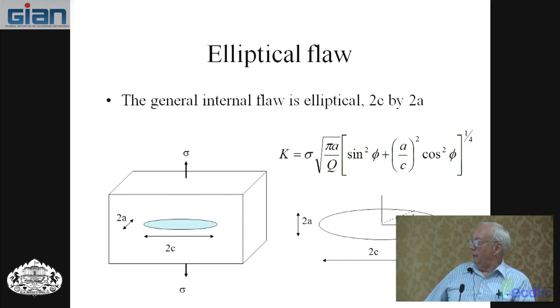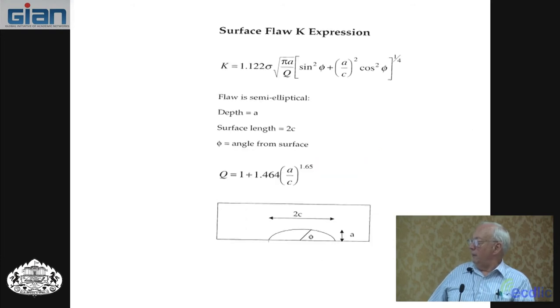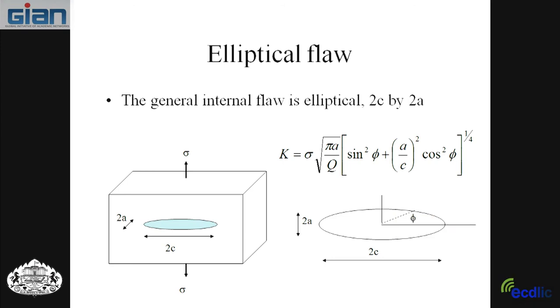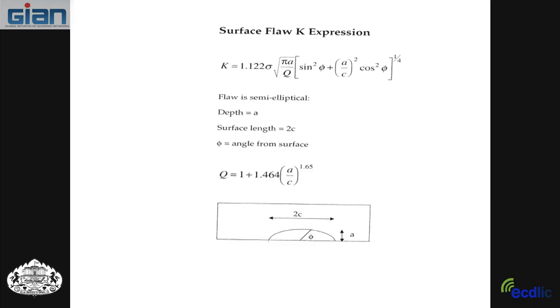Most often, though, this elliptical flaw is cut in half and you get the semi-elliptical flaw. Now, this is looking from top down here after you cut the thing in half, semi-elliptical flaw, so that the major axis is still 2c, and this is a semi-minor axis to the ellipse. And you have then this K solution. You pick up the 1.122 factor out front, that is for all surface flaws, and the depth then a, the surface length 2c, phi again is the angle from the horizontal. And so you need a Q factor, and this is an approximate Q factor.